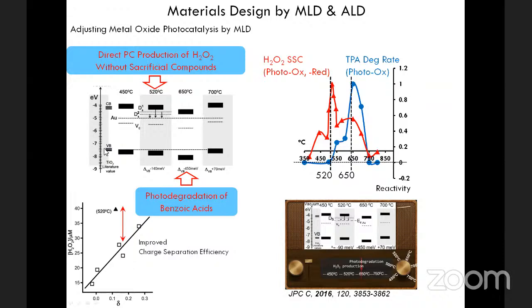For the hydrogen peroxide production, it also made it clear because these defect states allow to mediate electron transfer from the photoexcited electrons from the conduction band to the gold Fermi level, and therefore override the kinetic barrier that usually hamper the efficient photocatalytic reaction of titanium dioxide by having these intermediate states that facilitate electron transfer of the photoexcited electrons.